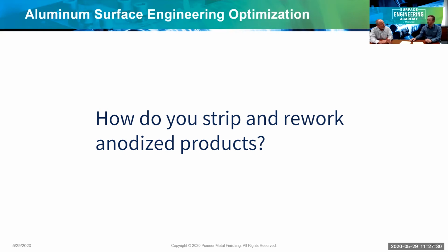Now, as far as repairing an area, there is some ability to have just selective areas machined off and expose the raw aluminum and then go back and start the process over again. You have to be careful though, because if you get near the point where the old thickness was of the coating, you can start attacking that old coating. So it was something that can be done, but quite frankly, it would be risky.